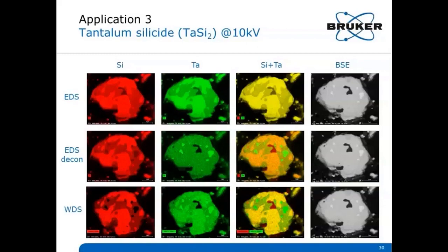WDS shows more variation in tantalum content than what EDS implied. So here we see not only the bright spots, but we see also differences in this area between somewhat lighter and darker areas. Furthermore, the silicon variation is more pronounced. So there's more contrast between the different areas. In conclusion, WDS provides more detailed information on sample heterogeneity.